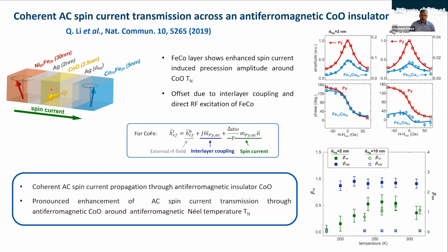And then by using the ferromagnetic resonance condition and by using the element specificity of the XMCD, we are then able to excite a spin current in the permalloy source layer and then individually measure the different elements and individually probe the response in the cobalt iron sink layer.